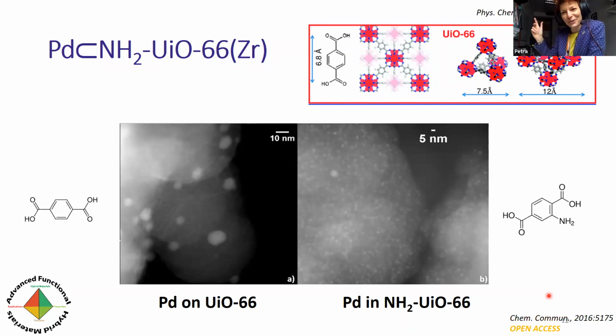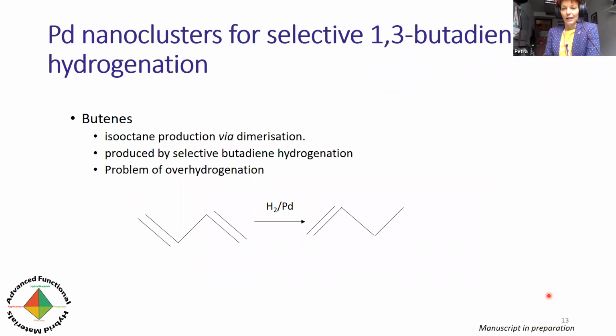And if you perhaps recall those clusters I was showing, if we had a particle of 0.8 nanometers, we only had 18 atoms in that. So perhaps we thought that might be a good model system in which we don't have a lot of interstices, and perhaps we can't form the hydride phase. So the reaction we decided to look at is the selective hydrogenation of 1,3-butadiene. And this is the reaction we ideally would like to carry out.